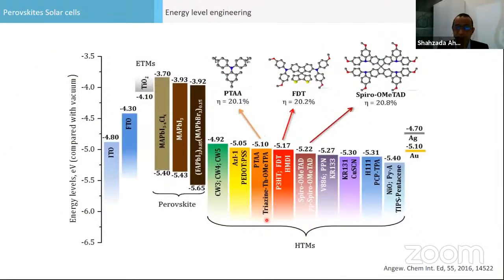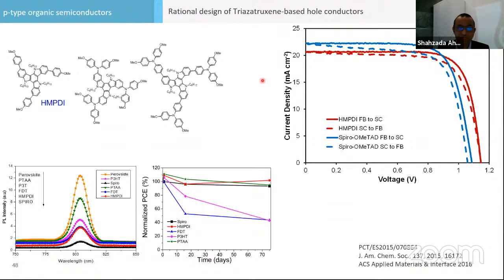So before designing any hole transport material, we take care of the band gap alignment, whether it's suitable or not. Otherwise, the charges will not inject. And this is the best performing, very old one, but FDT, Spiro, and the carbazole type materials. These are some examples we developed with triazatruxene based polymers long back, hole transport material, because it worked better than even Spiro at that point of time. We have a better one than that.